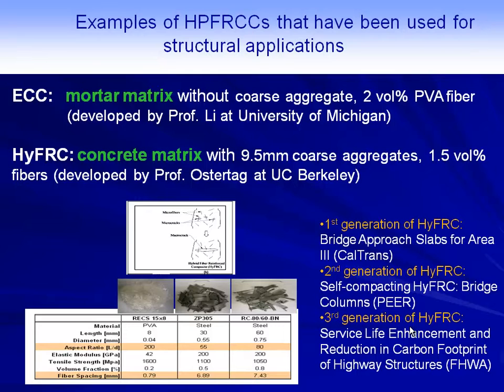Now we developed what we call 3 generations of these high-performance FRCs right now. The first one was for bridge approach slab in area 3. People are not familiar with area 3. This is an area with very severe environmental conditions. So we looked into that. This was our first generation. The second generation we developed for PEER, and this was for self-compacting hybrid fiber reinforced composites for bridge applications, for bridge columns specifically. The third generation we're developing for the Federal Highway right now, where we're actually looking at low carbon footprint. So we're using cement that is being replaced with a very high volume percent of waste material. The aggregates are recycled aggregates that have reactive aggregates in them. So this is a very, very new area to look into, a much more sustainable material. But the condition is that they still have to have a strain hardening behavior and deflection hardening behavior as before.